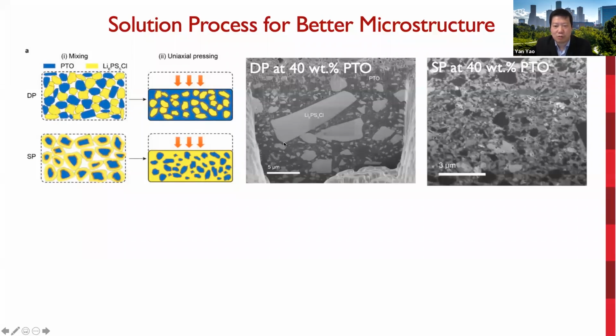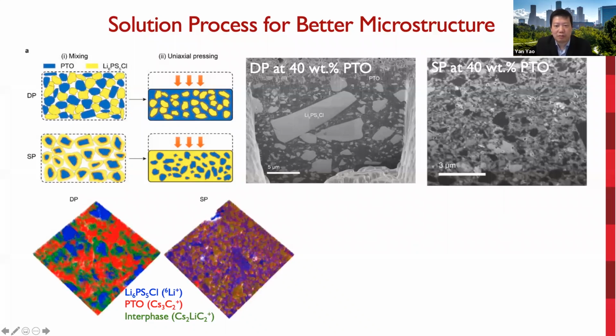The cross-section of the solution process composite at 40% active material shows that the phase separation is clearly reversed. Now the electrolyte domain forms a continuous network with the PTO domain embedded in between. This is in contrast with the dry process at the same PTO fraction. So although this is a solution process, we have to dry the solvent off in the oven to make it fully solid state. We also did the ToF-SIMS measurement.